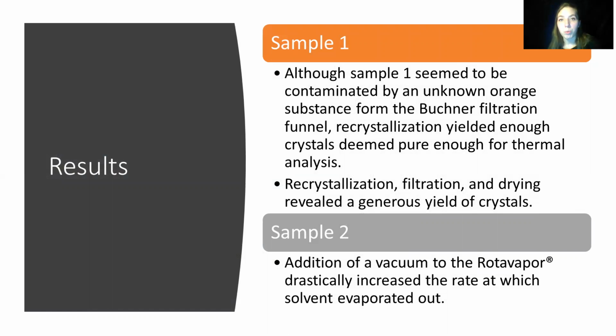Although the first sample was contaminated by an unknown orange substance found in the Buchner funnel at the time of filtration, recrystallization was sufficient to purify it, and it yielded a generous amount of crystals. There was enough present for thermal analysis in the DSC-50. During the synthesis of sample 2, it was discovered that adding a vacuum to the Rotavapor drastically increases the rate at which the solvent will evaporate out.